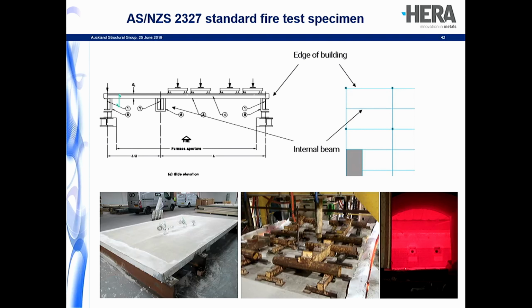And some pictures of a real test that I was involved in the UK, shown at the bottom here. So the bottom left one is the test specimen. This is it after it's installed over the furnace, and these are the loads. And this is at the end of the test, they tend to open the furnace door just to get the furnace to cool down quickly. And I took this picture very quickly without my camera melting, but that's essentially at the end of the test. So unfortunately, it's a pretty unspectacular test. Nothing really happens, but it's a way of actually measuring the fire resistance of the floor.